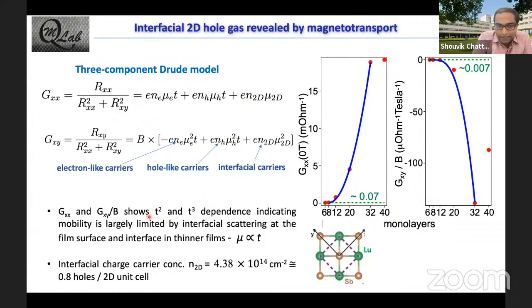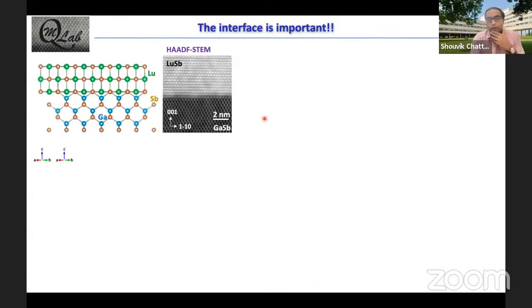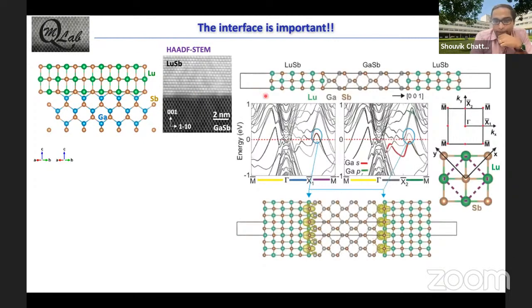And furthermore, you can see, just looking at the trend as a function of thickness, that the mobility scales with the film thickness in the thinner limit. That again tells you that here you are dominated by interfacial scattering, which limits your mobility or the mean free path. And that again tells you that in the thinner films, you are in a quasi-2D limit. Okay. So now we went back to doing the DFT calculations, but this time we explicitly took into account the interface here. And now we do see that there are interfacial states coming from the gallium s orbitals.